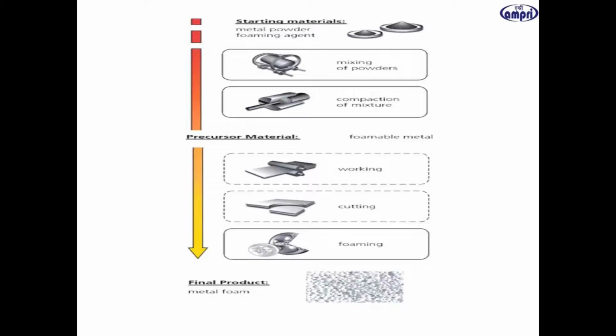So here you can get a section which is filled with foam, because you can get the precursor through this technique and then use this precursor within your desired component, and you heat it at the suitable temperature. This material will foam and fill that component which you want to fill with the metal foam.